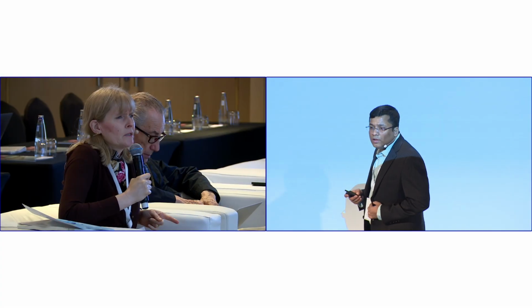Really nice talk, Bivas. I just wanted to know about the scandium nitride. You could change the carrier concentration quite a lot in that, but I missed how you do that. Oh, yeah. So scandium nitride is just a III-V semiconductor. When you don't dope any hole dopants, because of the nitrogen vacancies and oxygen, it shows high carrier concentration. So when we want to reduce carrier concentration, we basically dope magnesium, and magnesium is an extremely good hole dopant, so that can reduce carrier concentration very effectively.